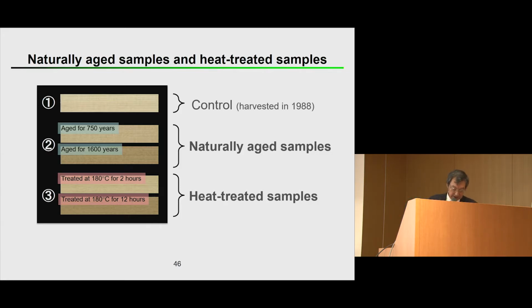Number 2 here is the aged sample for about 750 years, and this darker one is around 1600 years. Heat-treated samples, if you see here, at 180 degrees Celsius for 2 hours, and then this one is 12 hours. So the time span was very different from each other, but they behave very similarly, you see, in the change of the color.